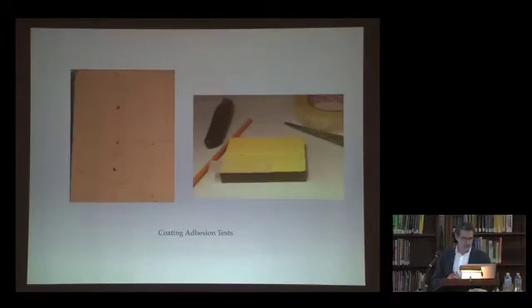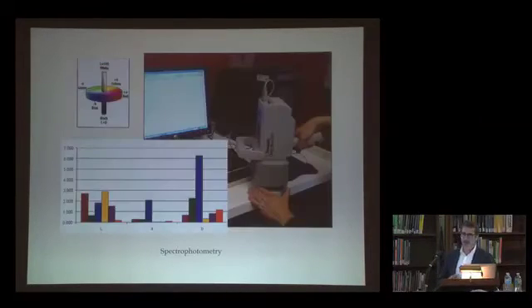So a few other tests where we wanted to test the adhesion of the different coatings, and we modified a standard test procedure for that. And we also wanted to monitor color and color change through each aspect of the testing procedure. So we utilized a spectrophotometer for that.